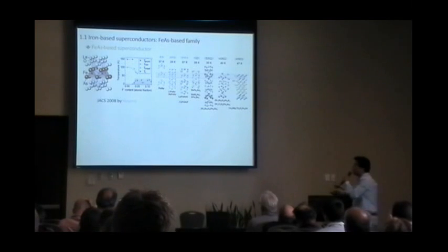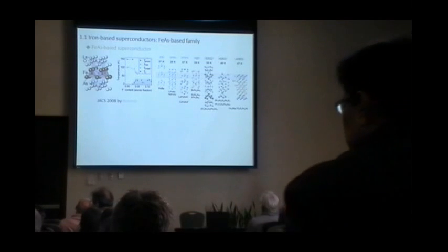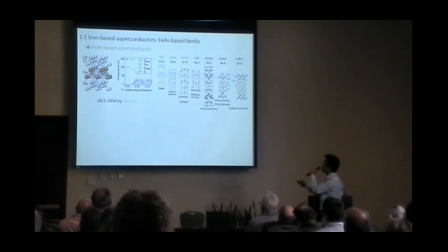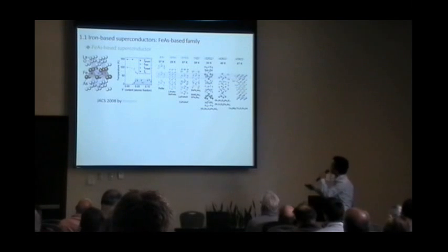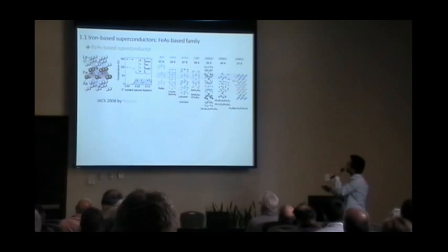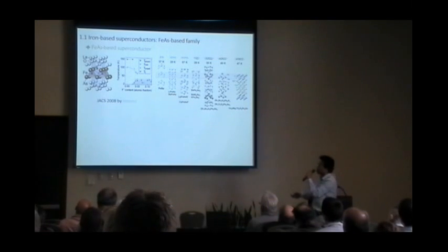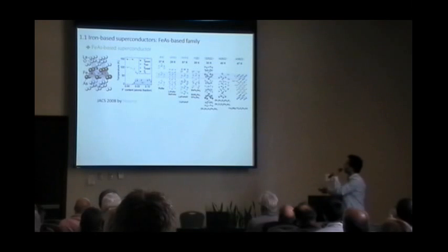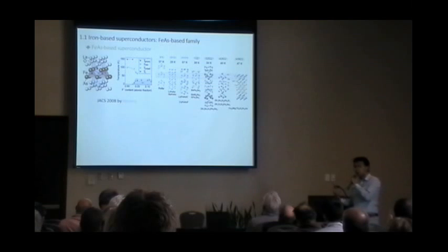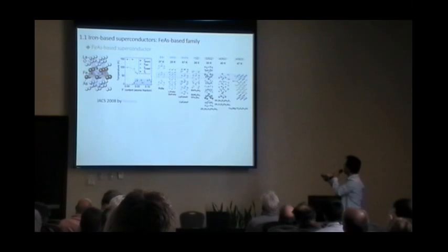As we know, iron-based superconductivity comes from 2008. This is the first iron-based superconductor. You can see it's typically a layered structure. Once this compound has been doped, the ground state is suppressed and superconductivity just shows up. So after almost 80 years, we can see iron-based superconductivity. Now it's a very huge family, and this is just some of them.